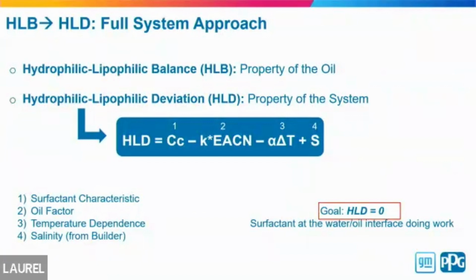So then, for HLB, we identified the surfactants, but we also tried to fine tune those surfactant package selections. HLB, as I mentioned earlier, is a property of the surfactant. Then we looked at HLD, which is a different methodology to screen for surfactant and oil, both of them. This is different. It's a property of the full system. That's a formula that identifies the HLD, just for your knowledge. Since it's a property of the full system, we are looking at the surfactant characteristic, the oil factor, then there is a temperature dependence, and also the salinity of the builder. And typically closer to 0 is better.